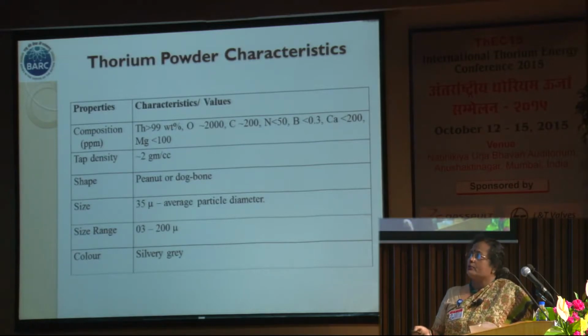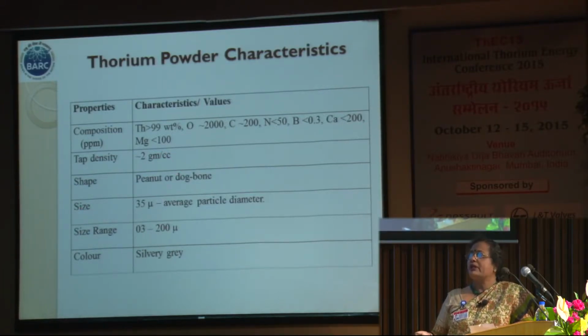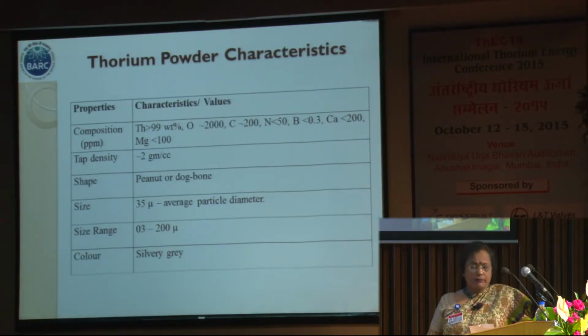Characterization of this thorium powder: purity is around 99% and oxygen content is 2000 ppm. Tap density is around 2 gram per cc. Average particle size is 35 micron, with a size range of 3 to 200 microns. The color was silvery gray.